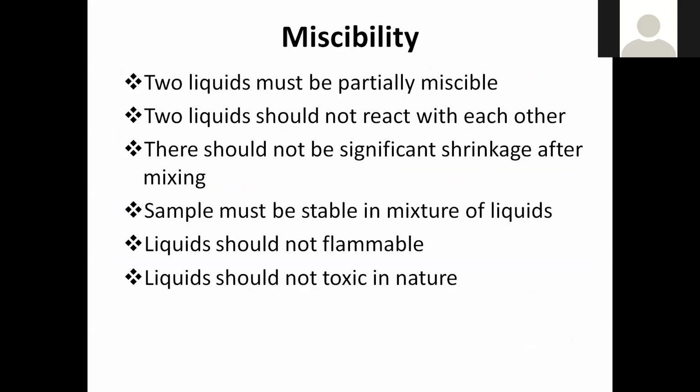Now, miscibility. Two liquids must be partially miscible. I was mentioning the same point. Two liquids should not react with each other. There should not be significant shrinkage after mixing. Sample must be stable in the mixture of liquids. Liquids should not be flammable, and liquids should not be toxic in nature.